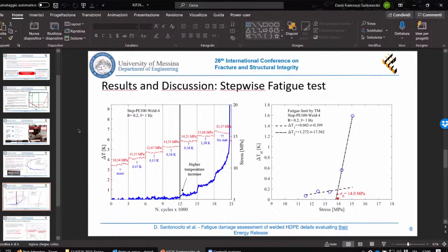Yes, of course, because we have to think that this methodology was applied at first on metallic materials, and it mainly depends on the kind of steel on which we are applying this methodology. We applied it on medium carbon steels as well as very low carbon steel materials, and we obtained wonderful results because the temperature signal was a really clear signal, and in addition also to polymers and composite materials.